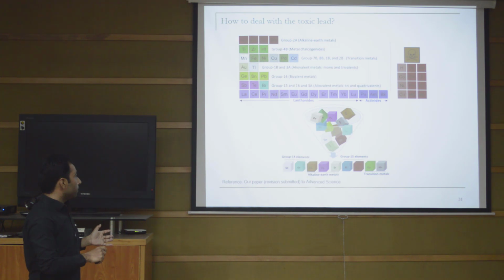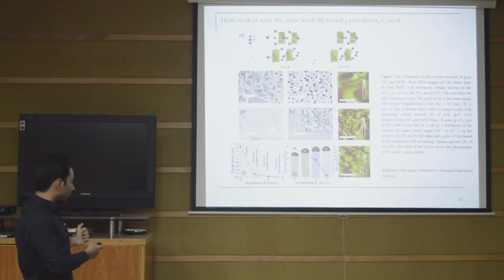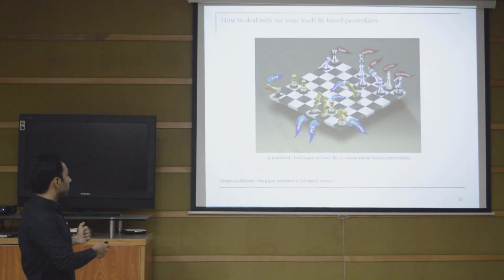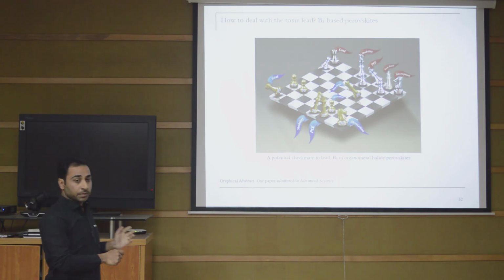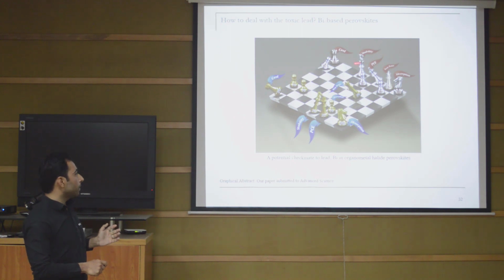And we have studied some electronic properties of these materials, and we have filtered that these materials are more suitable to be utilized instead of lead due to their comparable properties with lead. And indeed, we have chosen bismuth as a replacement of lead, and the reason is their cost is lower than that of lead, and they are more stable in the ambient environment.